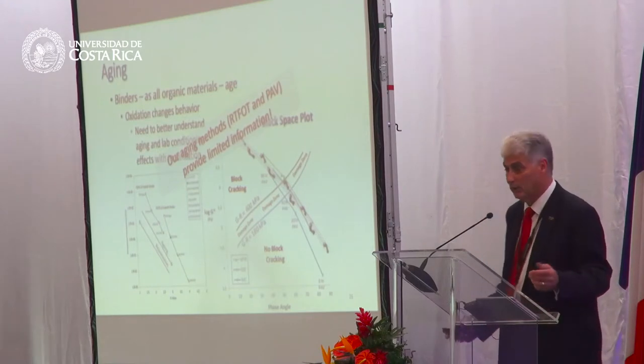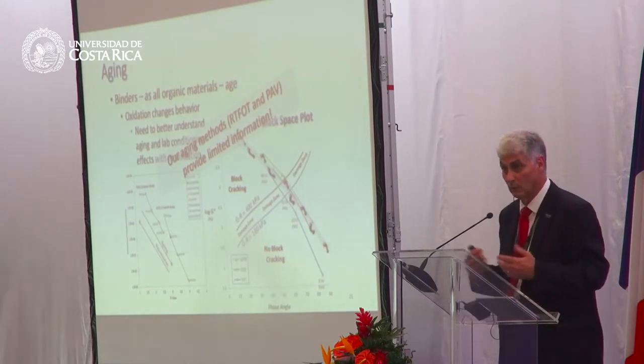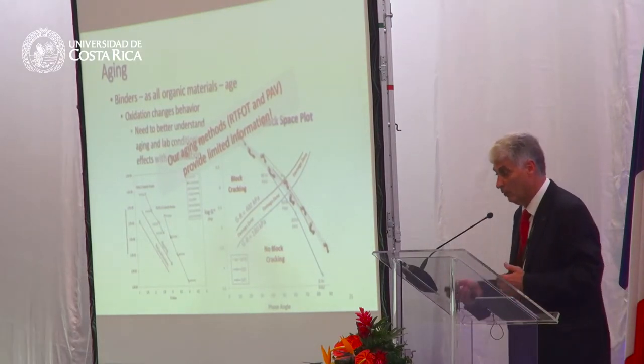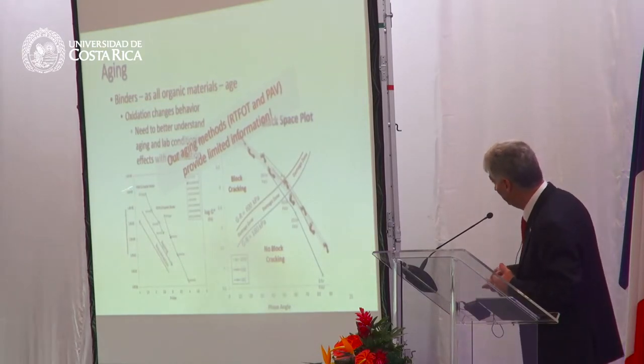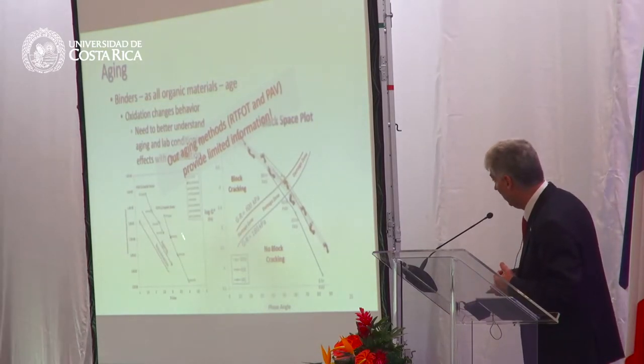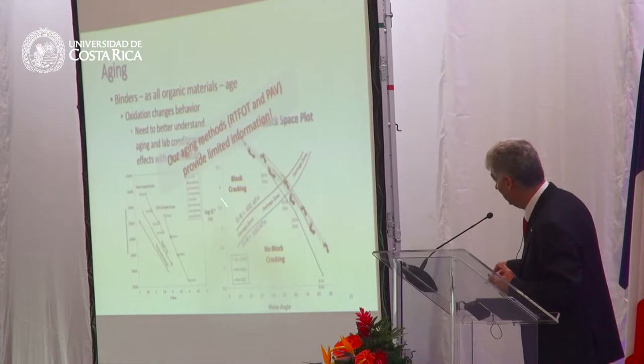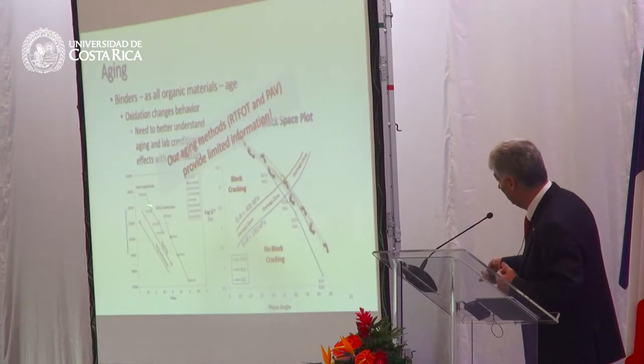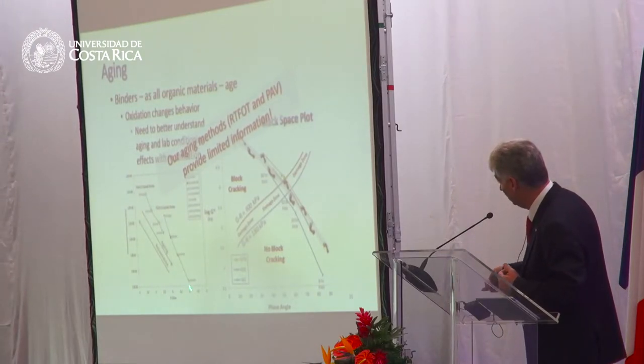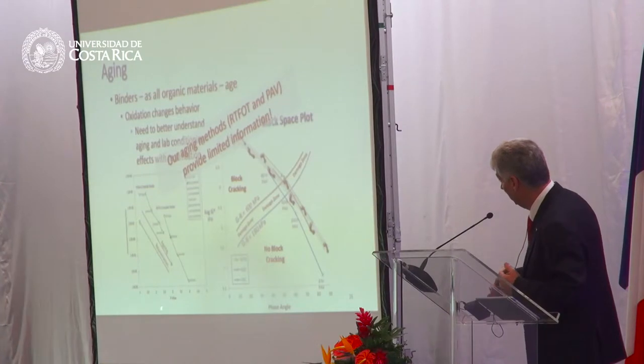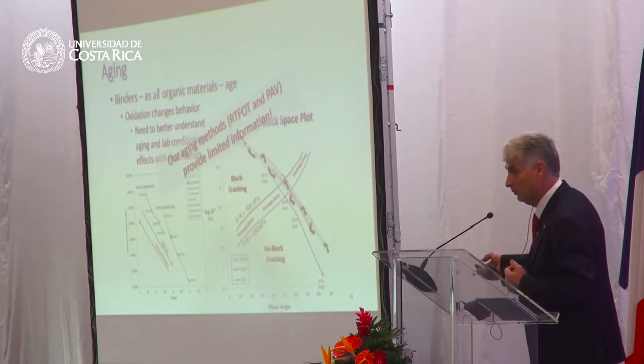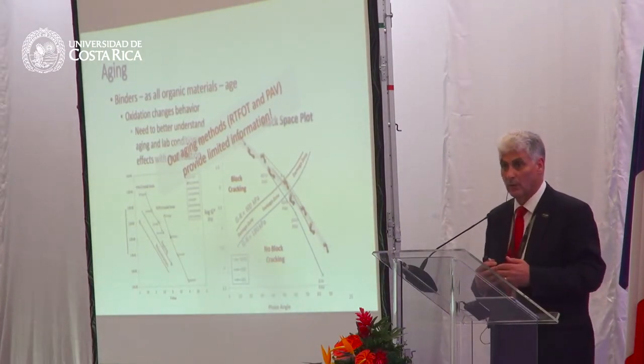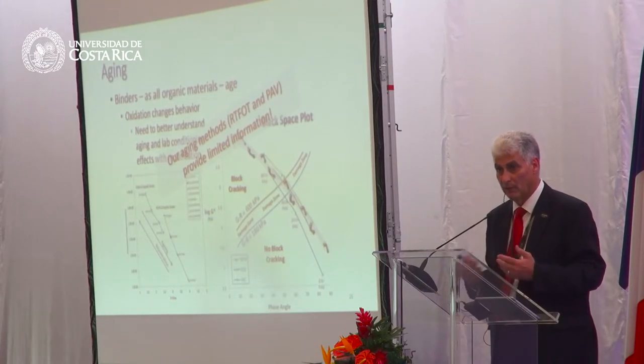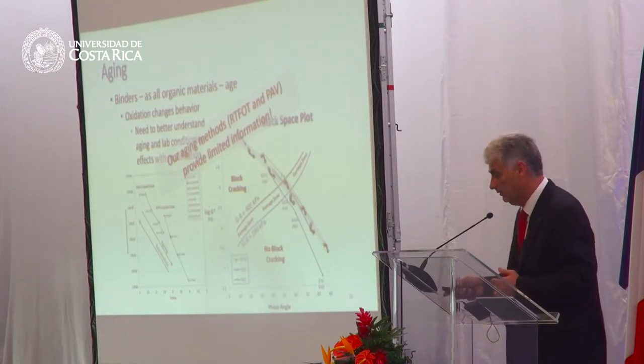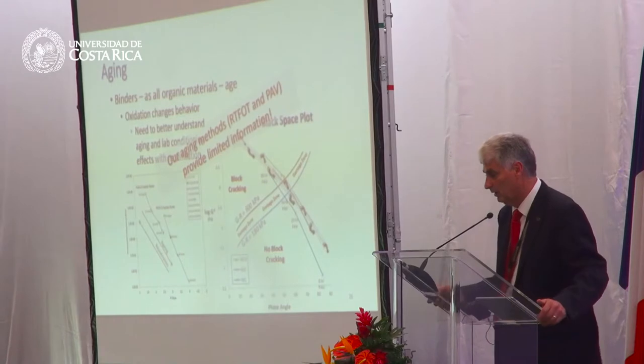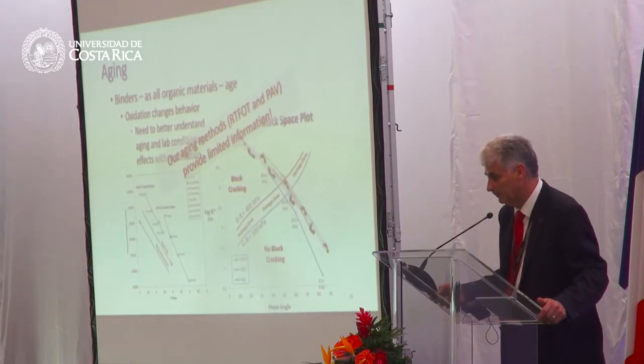If we're adding oils such as rejuvenators or we're using high RAP contents, we can use a process where we look at the R value versus the crossover frequency in this plot here. The materials as they age and oxidize will always move in one direction. If you want to rejuvenate, you will always move in the other direction. So by using rheology, we have some very useful tools for helping us understand and design asphalt binders.